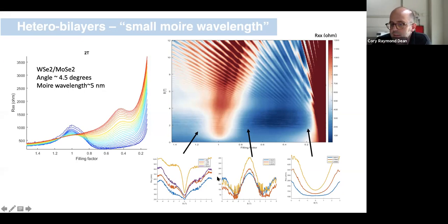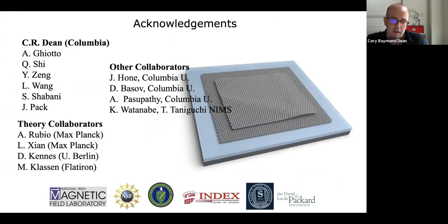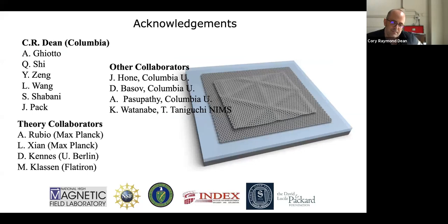So we again are tempted to interpret this as indicating some variation in the ground state order if we compare overdoped versus underdoped. And in particular, what's interesting to us about this is that it seems to suggest it really is a universal behavior in these systems, independent of what precisely makes up the material combination. These flat bands seem to be well-defined flat bands whose character might be well captured by simple theory. Okay, let me finish there.